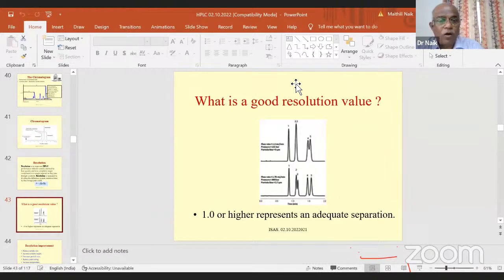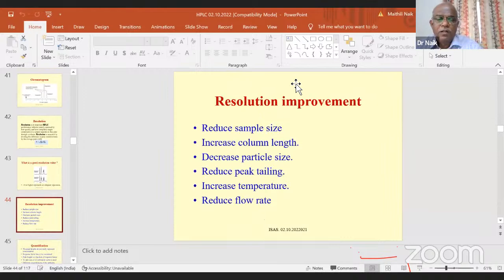And while optimizing the conditions of HPLC analysis, one has to choose the solvent, flow rate, and column in such a way that the resolution is always 1 or more than 1. If you want to improve the resolution, then you have to reduce the sample size, increase the column length, decrease the particle size, reduce peak tailing, and increase the temperature. Yes, I can mention that also. There is an oven available which can be kept around the column, and you can heat the column if required. This facility will help in improving the resolution. Then reduction of the flow rate can also lead to the improvement in the resolution.